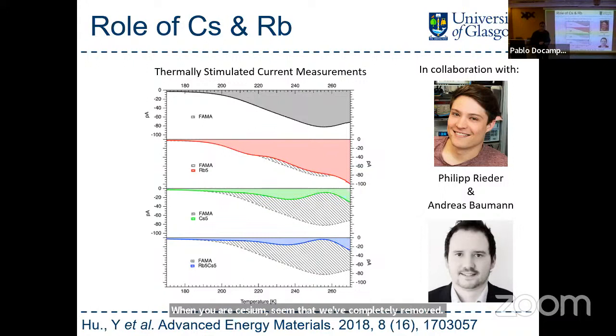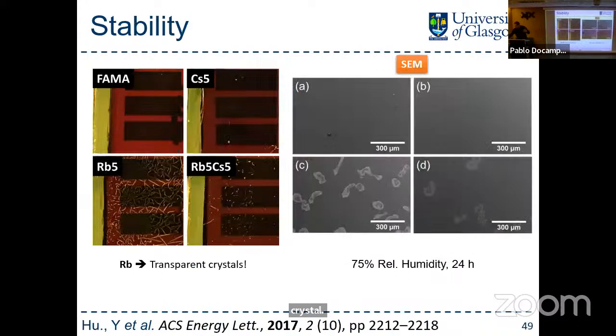So it turns out that when you include cesium in the structure, you heal some of these deep traps, which explains why your charges become longer lived. There are fewer traps to recombine, so you end up with a better device. The fact that rubidium and cesium work better in tandem is because rubidium stays on the surface of the crystal, passivating, removing some of that grain boundary disorder.